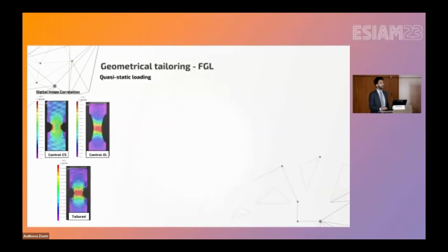Then we performed mechanical testing. First, static. If you look at the semicircular notch, we can see that we have a localized strain, localized deformation, something that my colleagues in fatigue and fracture and I love. That's why we go for localized failure criteria. On the other side, for the elliptical specimen, the deformation is quite uniform, like a smooth specimen. That's where the global methods work.